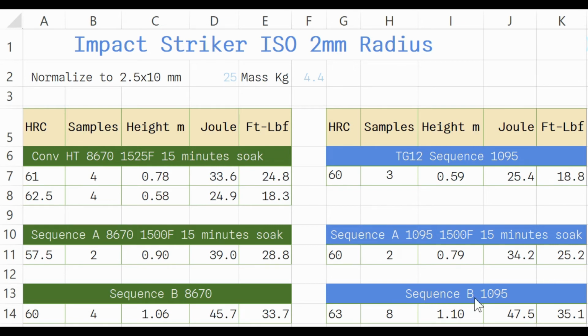Interestingly, compared to the 1095 sequence, notice the hardness is 63 Rockwell, with 35.1 foot-pounds. I got multiple samples, so they average over. Some numbers are very high, some a little low, but average out to be 35 foot-pounds. Compared to 8670, where the highest I have is just one number, at 33.7, but that's 60 Rockwell, and this is 63 Rockwell.